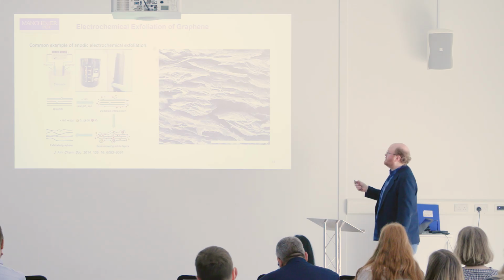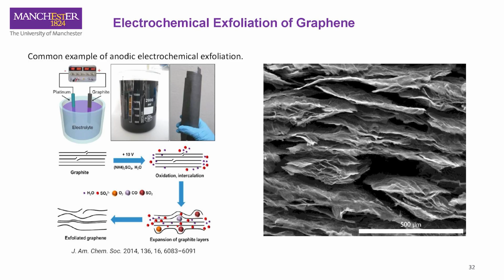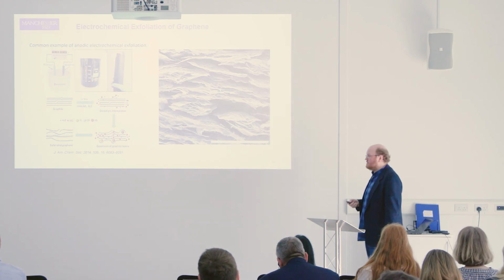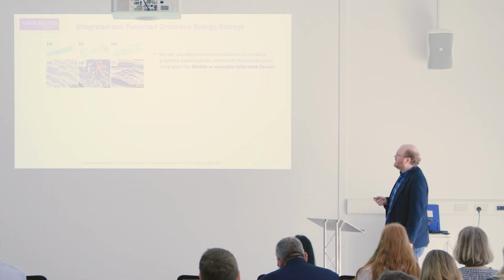So what you can get is a structure like this. This is a graphite foil. It's partially exfoliated, and then we stop the experiment. And you can see that each of the layers is being slowly pushed apart. Obviously, if you keep on going, you can completely exfoliate this, or you can tune the amount of exfoliation or that interlayer spacing, depending on which ions you intercalate into it.